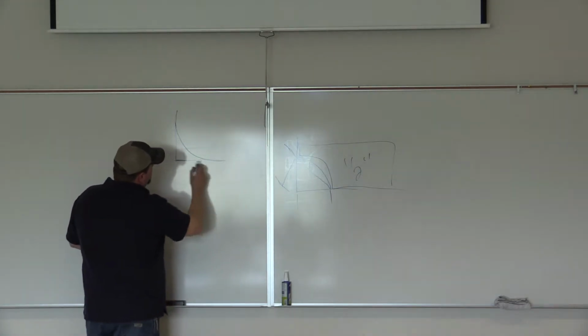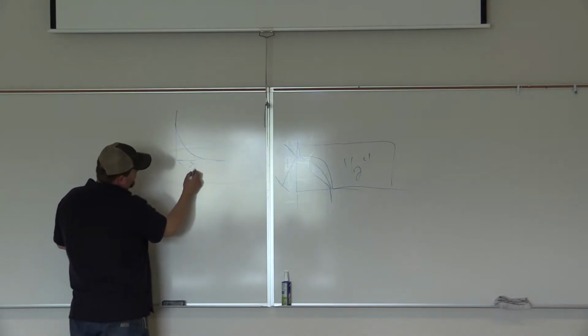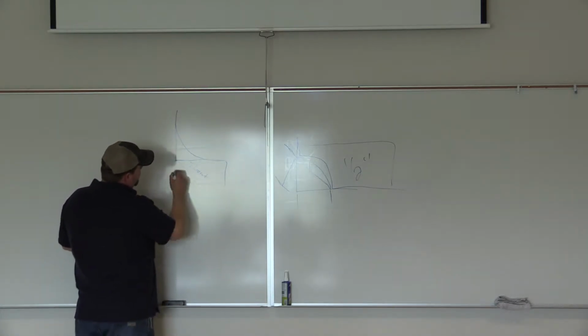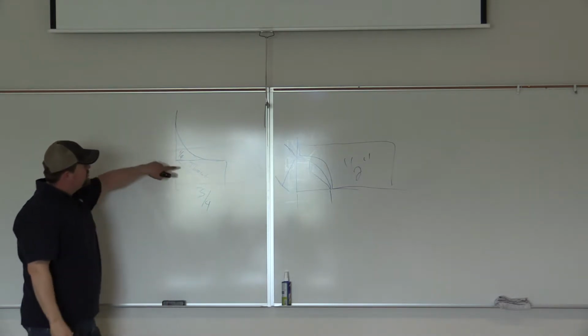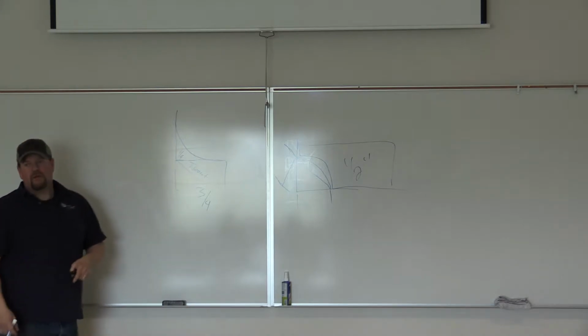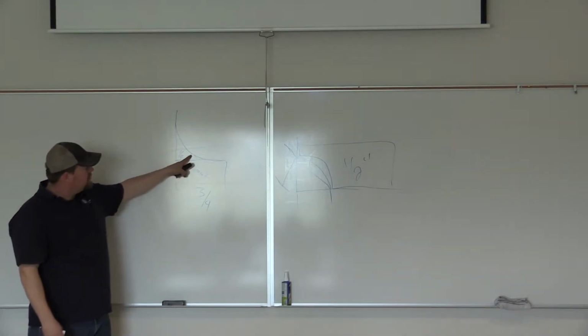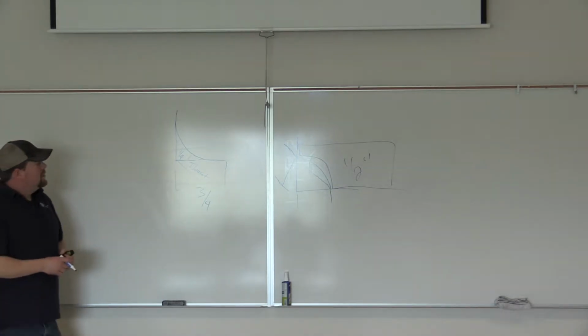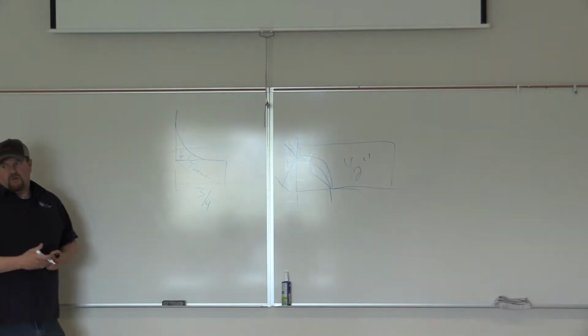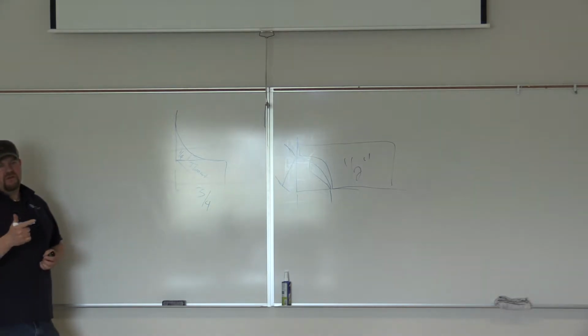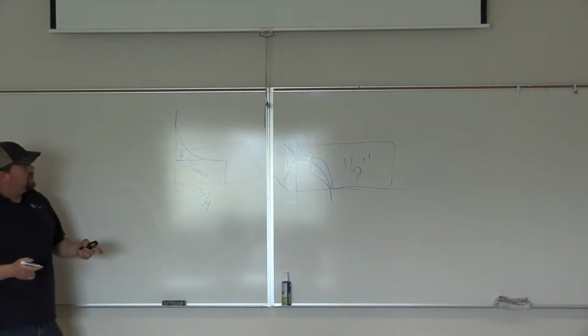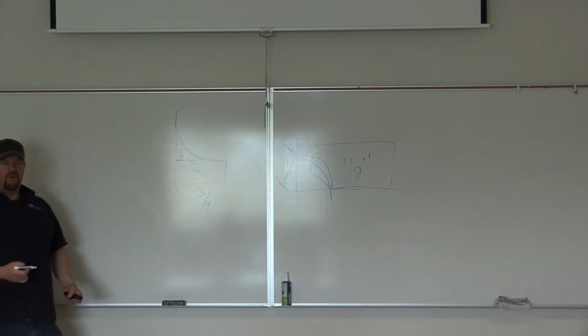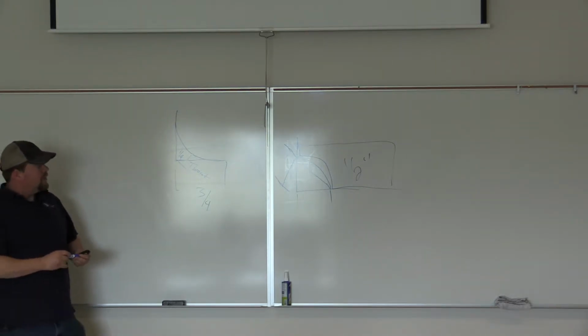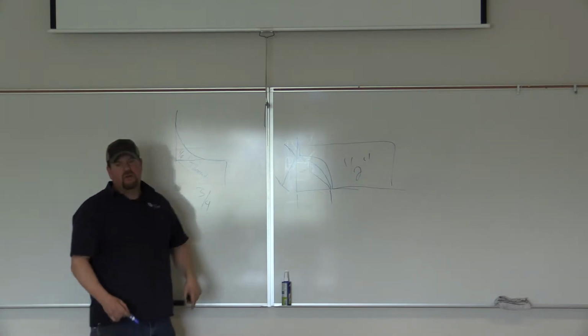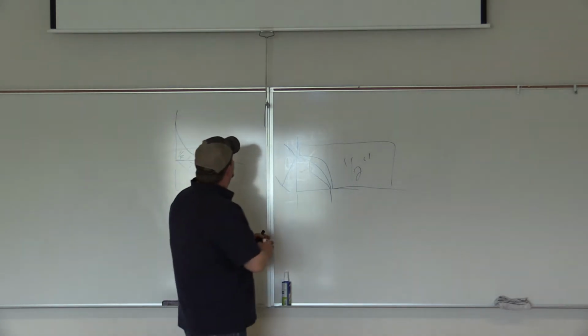Okay? So looking at this, there's actually the throat dimension. And if we went off leg to leg, this might be 3/4 of an inch, but the weld size is actually only 1/4, so this is your weak point right here, right? Actually, in this case, it ends up being right along this edge here, okay? So those are the first two ways I decide how I'm going to measure that weld, convex or concave. It's also what I know the inspector's going to look for from the welding perspective too. You know, I know it needs to be at least flush, slightly convex, right? Perfect.